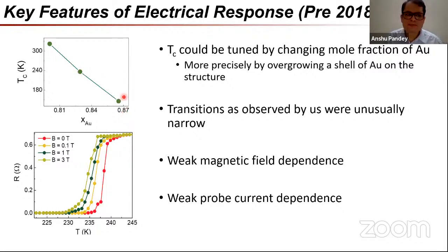And what we found was, as we did that, how we did it is a little bit tricky, and I'll come to that in just a moment. But as we increase the gold fraction in these materials, the temperature at which it drops to zero resistance falls. And of course, then we started to also see a normal state where this would behave more as a conventional metal.